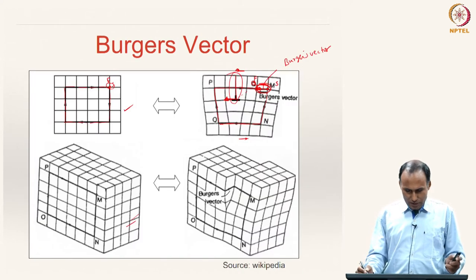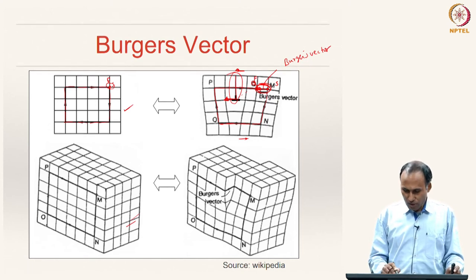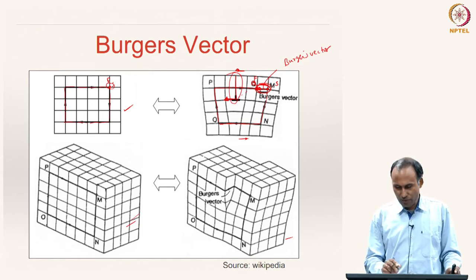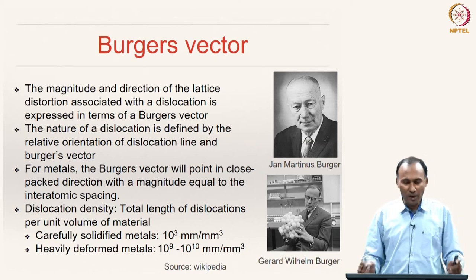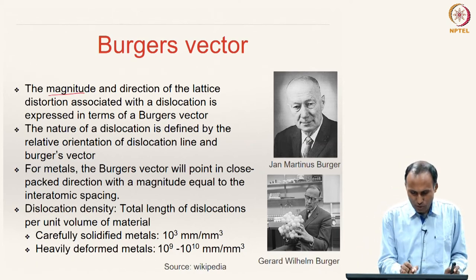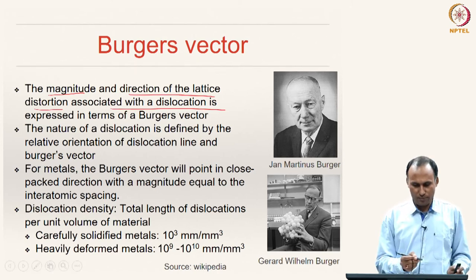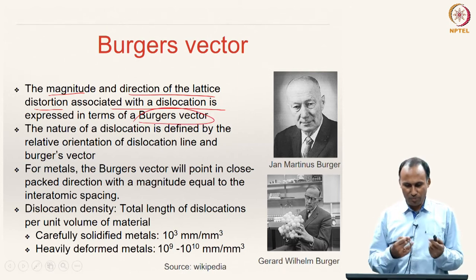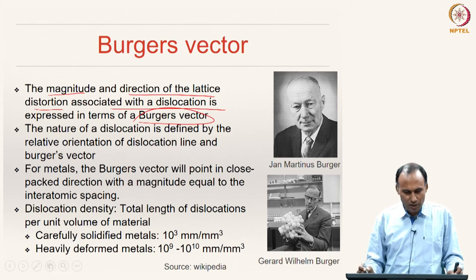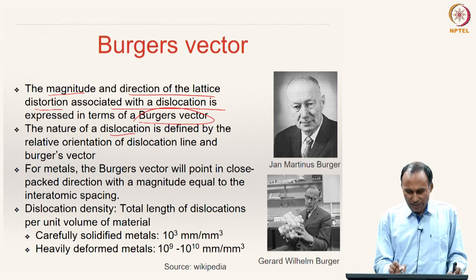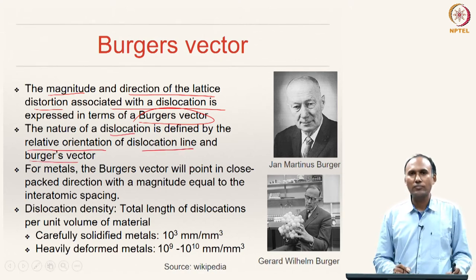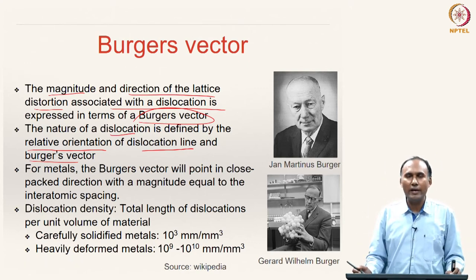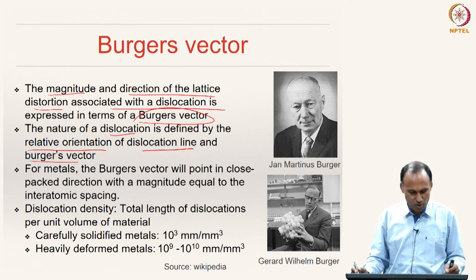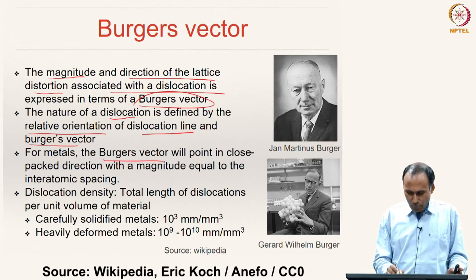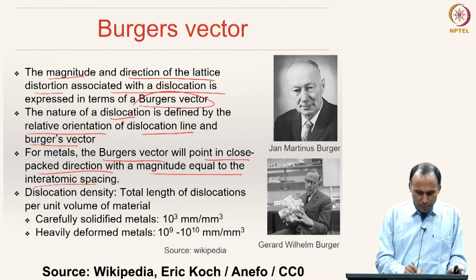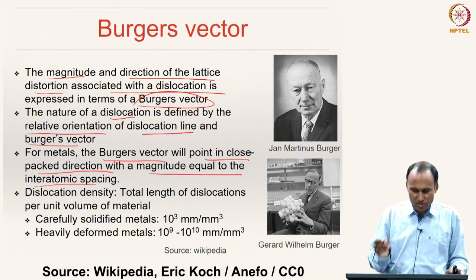All right. Now let us look at the Burgers vector in the case of screw dislocation, not here but at a later stage, where I will show you a detailed view. So what is the meaning of Burgers vector? The Burgers vector describes the magnitude and direction of the lattice distortion associated with the dislocation motion. And the nature of the dislocation is identified by the relative orientation of the dislocation line and Burgers vector. When the dislocation line and Burgers vector are perpendicular to each other, it is called an edge dislocation, as we have seen here. And for metals, the Burgers vector will point in a close packed direction with magnitude equal to the interatomic spacing, because the close packed direction is the direction in which slip takes place.